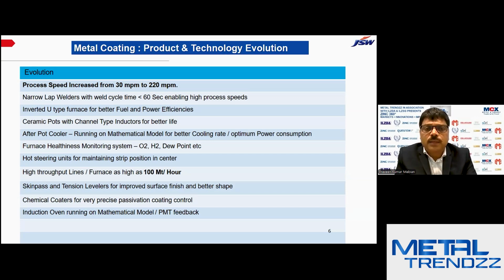And you can see the conventional welder. I'll show you a couple of photos later. The conventional welder takes a welding time of more than 1 minute. Right now, the welding cycle is close to 30 seconds. So if it is less than 60 seconds, you will be able to ramp up the speed of the metal coating lines. We have also made investments on the furnace part in order to get fuel efficiency.